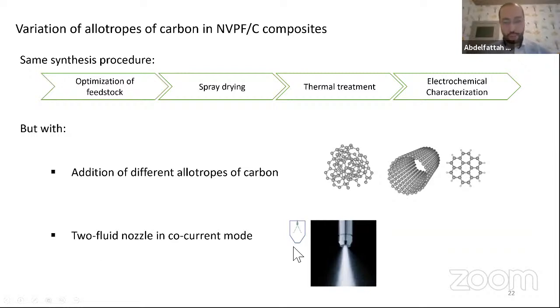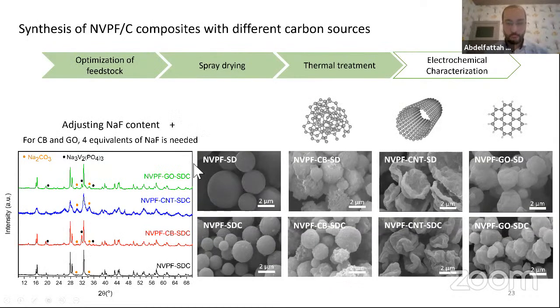And also, in order to decrease the particle size by using only the spray drying method, we changed the nozzle type. And we can see that here, for the one without any carbon, we have spherical particles. With carbon black, we have spherical particles, but with a rough surface, different from the one without any carbon sources, and the one with graphene oxide has slightly deformed spherical particles. You can see that for all 3 carbon sources, we prepared almost pure material.